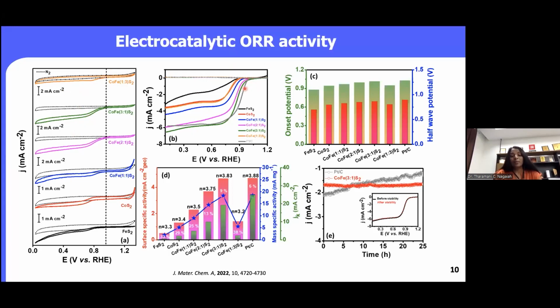As you can see, for the cobalt iron with 3:1 ratio, the onset potential is almost close to the state-of-the-art catalyst, and the diffusion limited current is also quite high, and the other variants are also quite close to this catalyst. However, a small amount of hydrogen peroxide is produced in the case of cobalt iron as well as the other variants. If you compare the onset potential and also the half-wave potential with respect to the state-of-the-art catalyst, the cobalt iron 3:1 stands out to be the best and is almost comparable in both half-wave potential and onset potential.